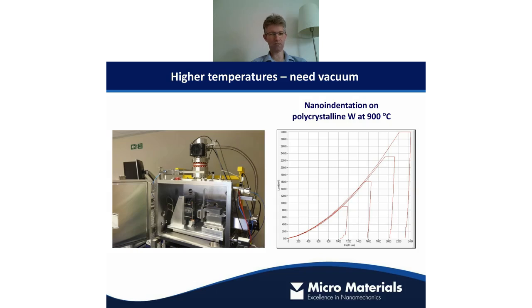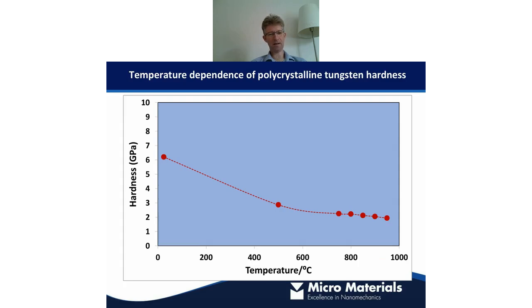And we've used this to do indentation tests, as shown here, showing tests at different loads on a polycrystalline tungsten sample at 900 degrees. And you can use this again to pull out the mechanical properties as a function of temperature. In this case, this is the hardness from similar tests. And you can see it's non-linear on tungsten. That shows it's very difficult to predict. So if you just had even these 2 measurements, it would be difficult to predict what was going on here. So it's really beneficial to be able to test over that entire range. And that's what the Nanotest Extreme gives you.